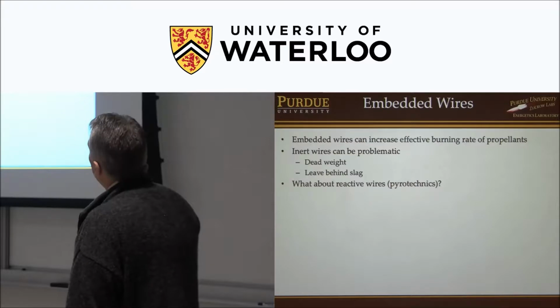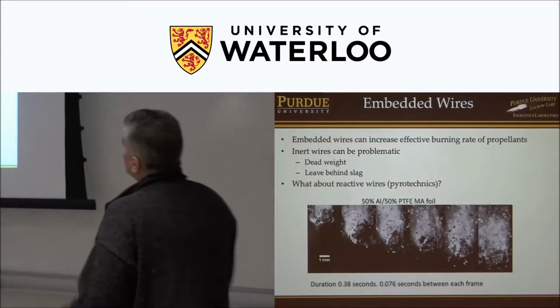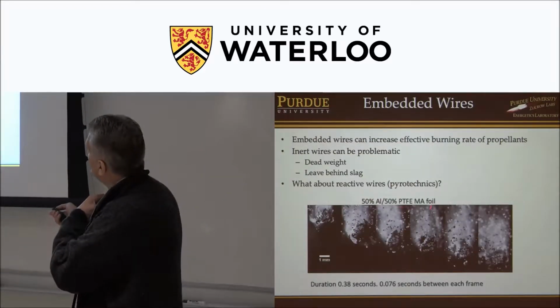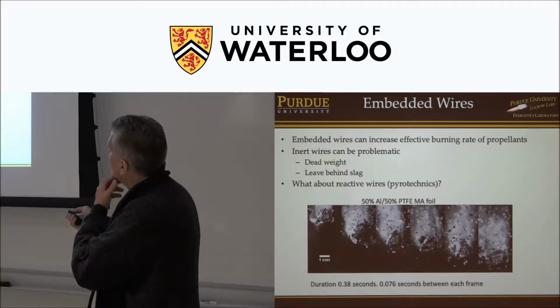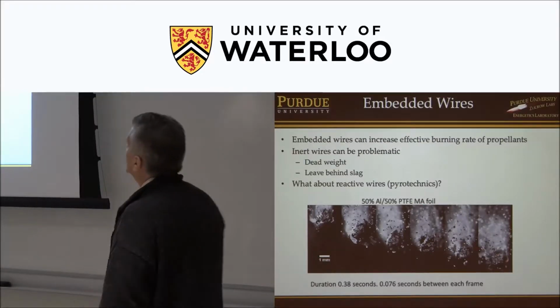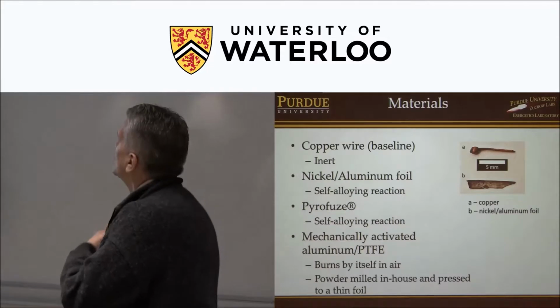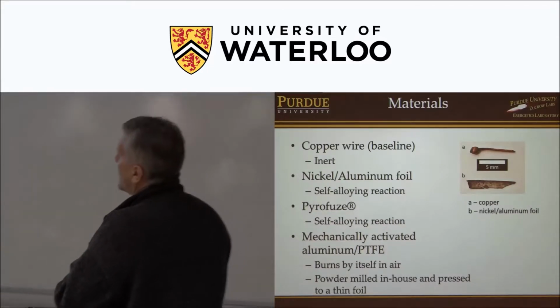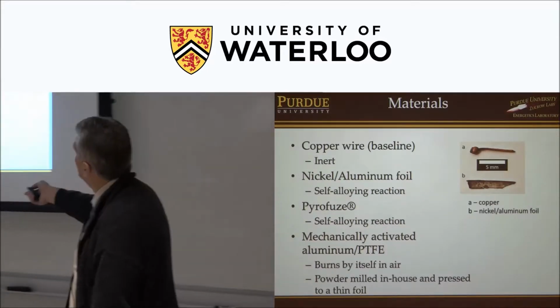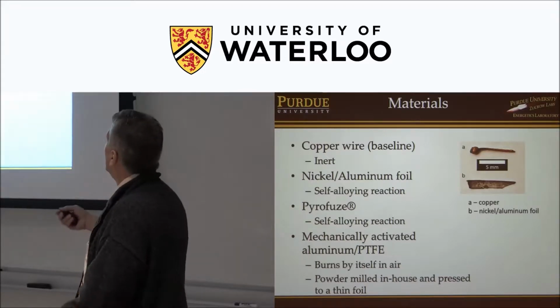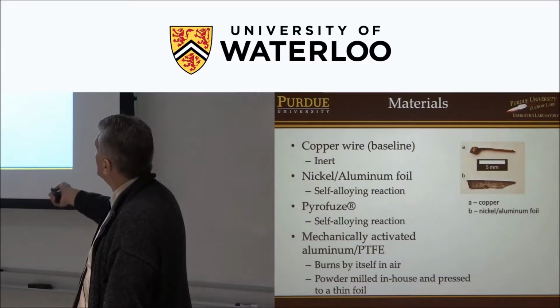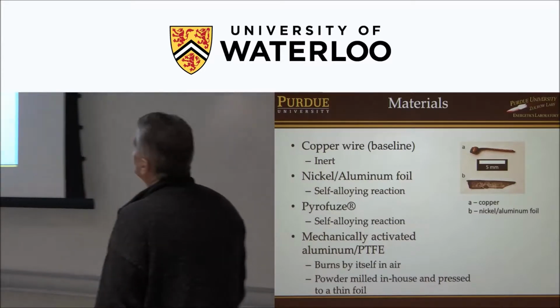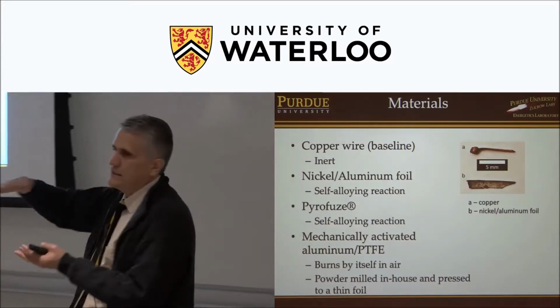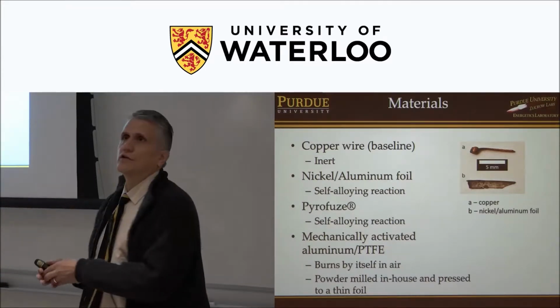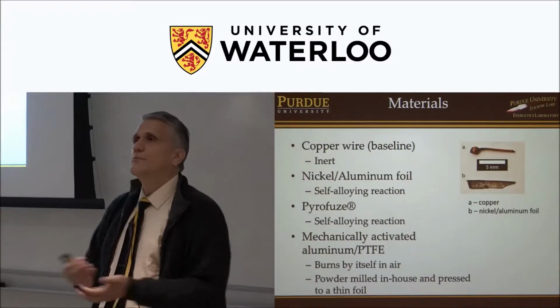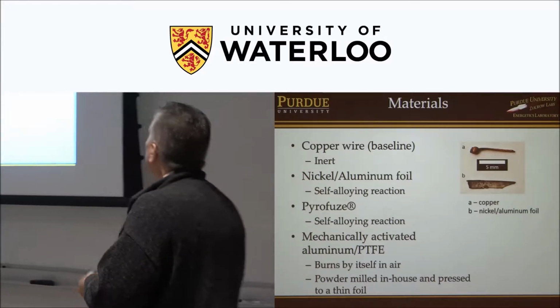So what about reactive wires or pyrotechnics? This is 50% aluminum, 50% Teflon, and we made this into a foil. This is just burning by itself. We've looked at putting different wires into propellants and comparing them. The copper wire is just a baseline inert wire. There's a nickel aluminum foil that's a commercial product. It's vapor deposited, nanoscale layers of nickel and aluminum. That forms an intermetallic reactive material.